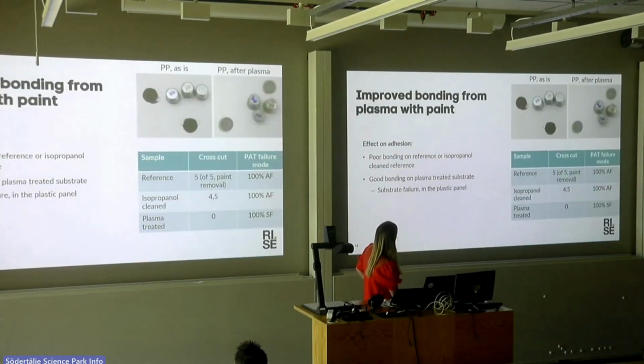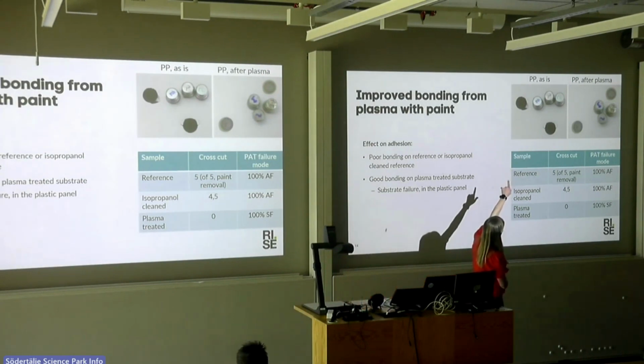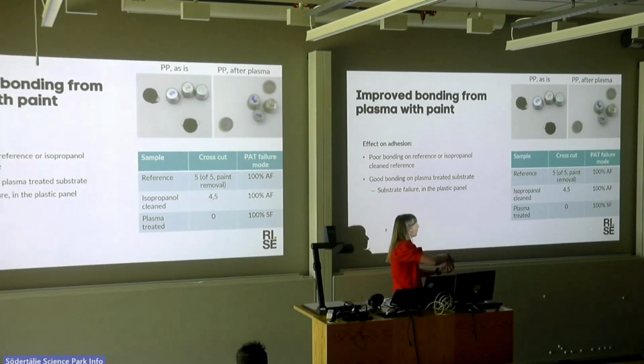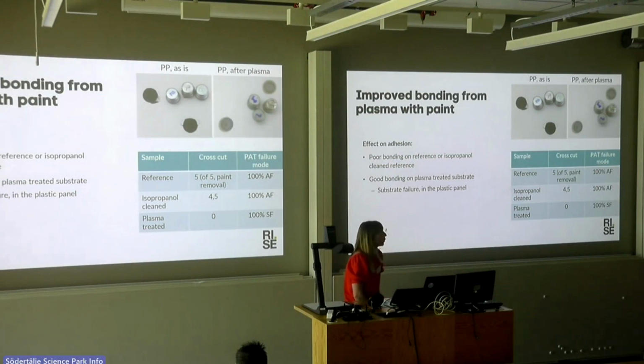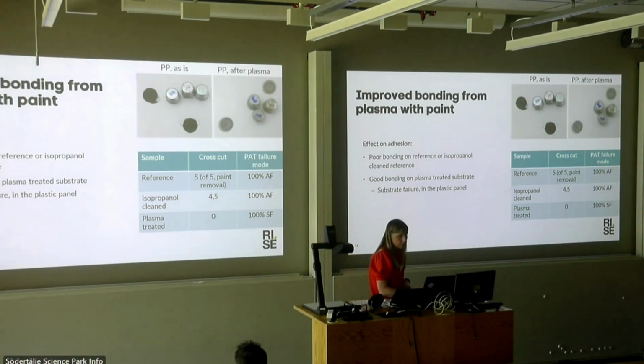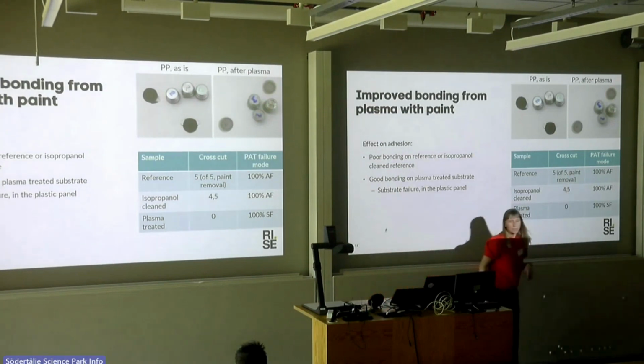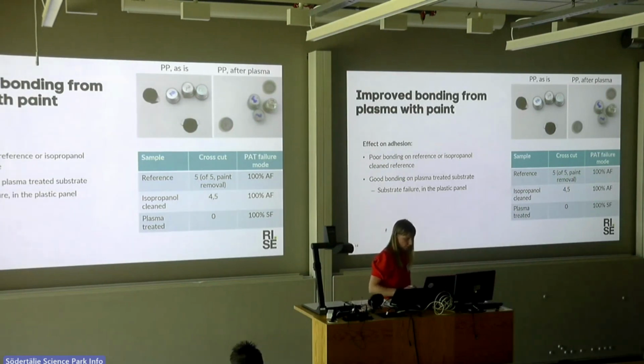I just want to show also improved bonding, how it can look if you do this. You glue a dolly to the surface, and then the polypropylene as is. Here you see the polypropylene surface is black, and then you pull with pressure, and the coating gets off. In the illustrative picture to the right, you get the failure in the substrate instead. The gray part is the plastic, so the failure is in the plastic substrate.